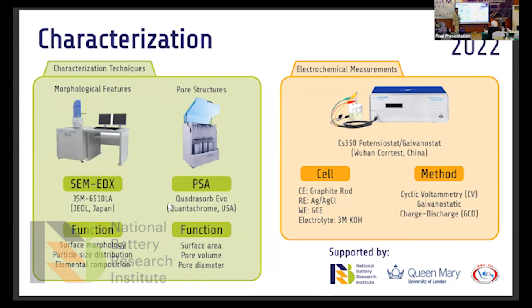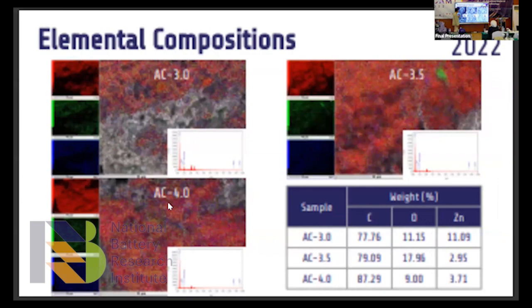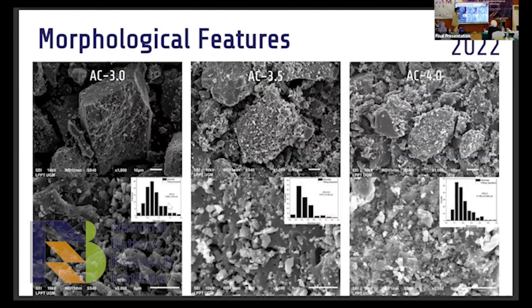Okay, so you have the SEM. Can we see the SEM result? Can you explain which one is the best, and which part is your carbon here? From the SEM result, the best is AC3. Why? Because we can see the particle is not yet broken, and it still has a bigger pore size. But in AC4 the particle has broken, and we can see the pores are covered or enclosed by the broken particle.